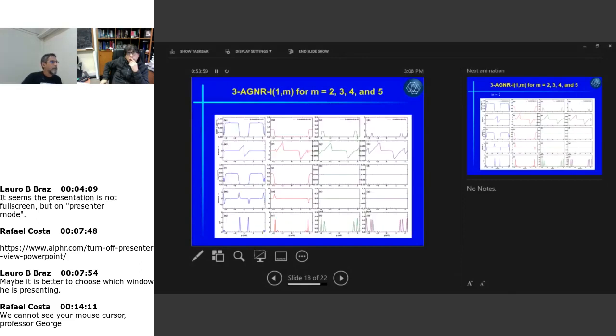Then we kept capital N equal 3, lowercase n equal 1, and then we varied m from 2 to 5. So this is m equal 2, m equal 3, m equal 5. So we see here that we kept the same ZT as before. We get a ZT equal to 6. Here we get a ZT of the order of 5. Here, for some reason, it's not clear to us why this happened, because this is a semiconductor, as you can clearly see on the top panel. For both of them, we get very, very small thermopower, very, very small Seebeck coefficient. And as a consequence, we have ZTs here that are basically zero. See that in the scale here, there is a 10 to the minus 4 on the left axis.